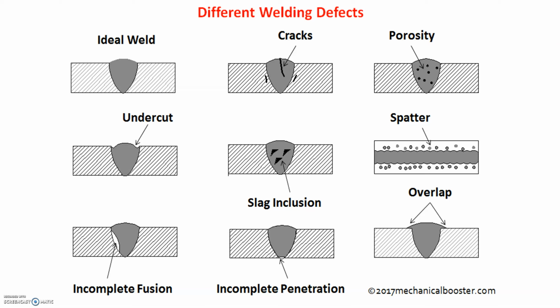Few welding defect corrections. Incomplete penetration. Primary cause is not enough current or wire feed speed. For electrode stubbing, you got too much wire, decrease the wire feed speed. Wagon tracks is from tip to work distance too close or shielding gas flow rates too high.